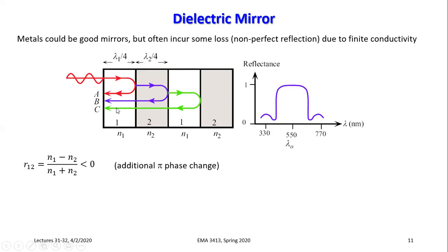Okay, and then remember, because the index of refraction is different, the corresponding wavelength for the same incident wave will be different as well. Lambda is the free space wavelength divided by the index of refraction. So if you have a smaller index here, the thickness will be slightly greater. But regardless, as a light wave propagates through, you have a quarter wave, so that means you have a half pi phase angle change. If you reflect it back, well, when you have this interface, you reflect back, then the incident wave and the reflected wave will see a pi phase angle difference.